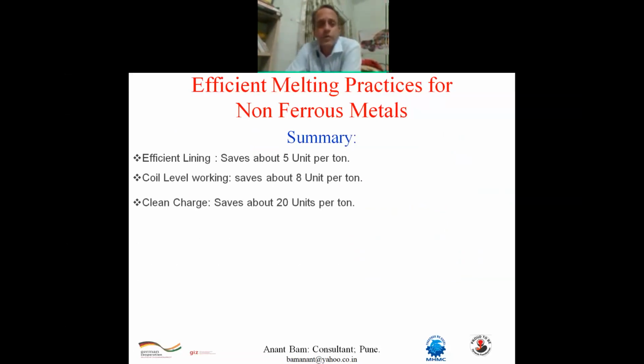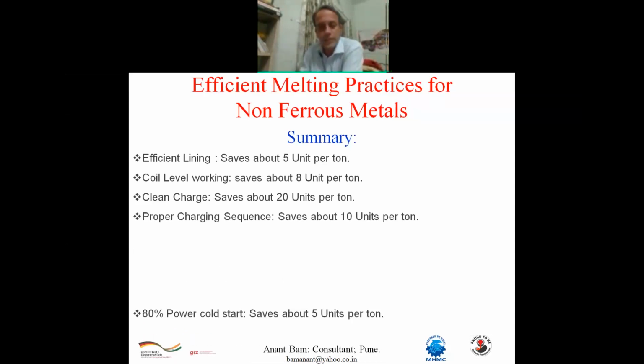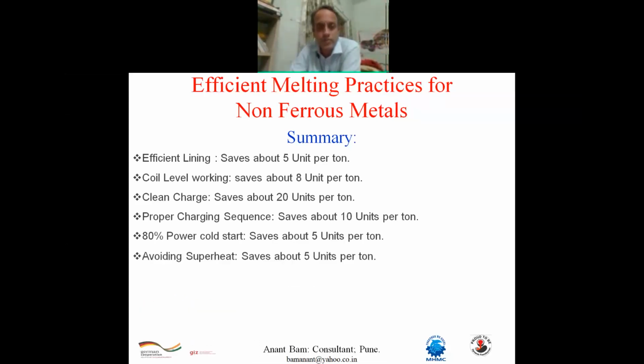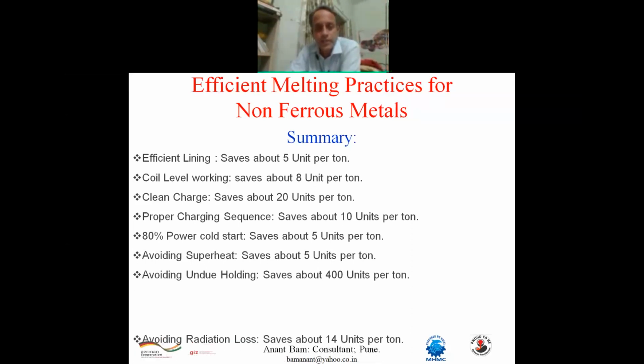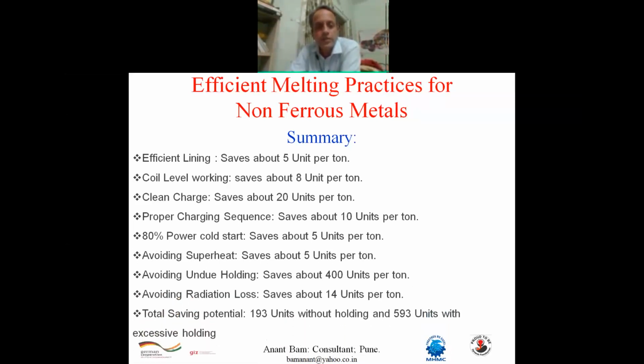Now we are coming close to the end of this presentation. Let us have this summary sheet. Whatever was explained in the earlier slides, a single line is the extract of that. Efficient lining or effective use of lining saves about 5 units. Coil level working saves about 8 units. Clean charge saves about 20 units. Proper charging sequence saves about 10 units. 80% power cold start saves about 5 units. Avoiding superheats saves about 5 units.